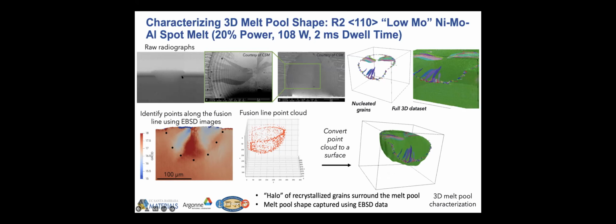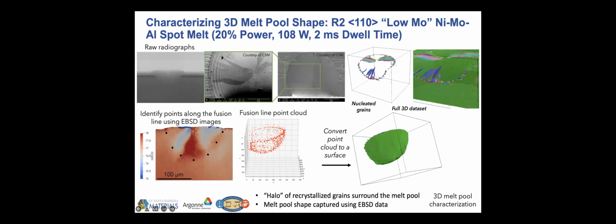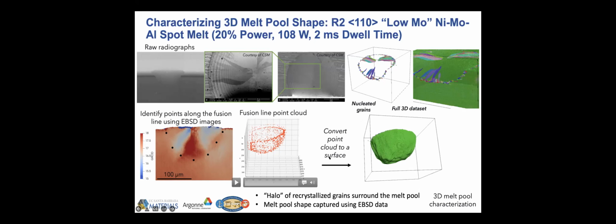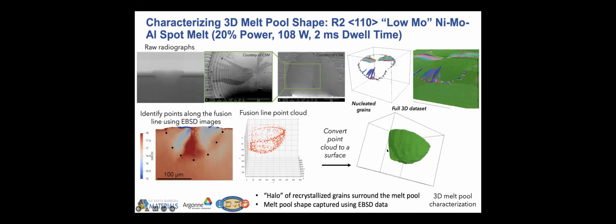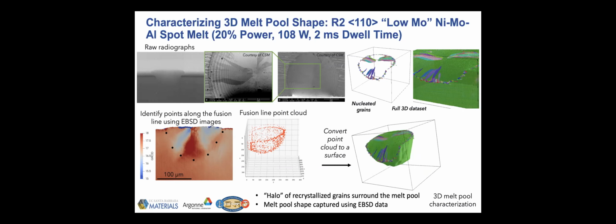So over here on the left is a well-behaved melt pool where again, we can see solid liquid interface velocity. Looking top down, we see these elongated columnar grains that extend from the edge of the melt pool inward in this case. Here we're able to use the tri-beam data to make a fusion line point cloud and convert this to a surface and have full crystallographic information in 3D about the grain structures we developed. Why do we care about this? We want to compare this to what we see in 2D, and then we want to use this to compare to our modeling that we're doing as well.